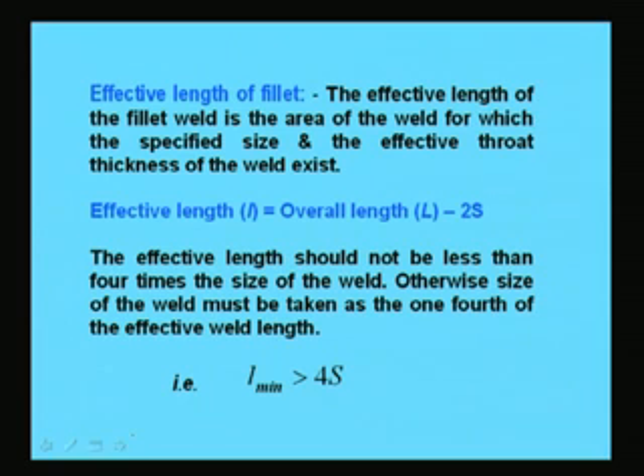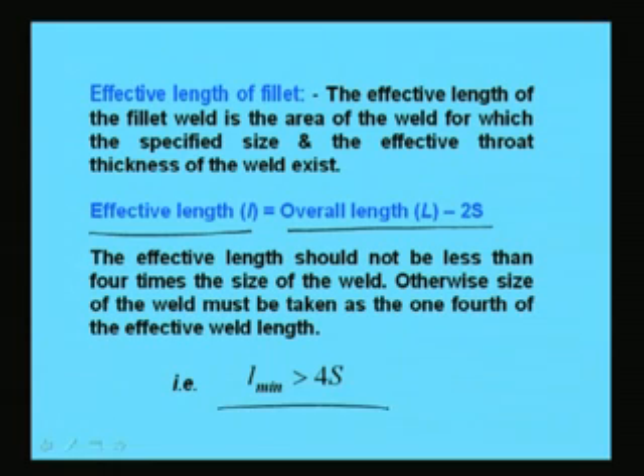Now, another important parameter is the effective length. The effective length of the fillet weld is the length for which the specified size and the effective throat thickness of the weld exist. That means the effective length will be the overall length minus 2s. So when we calculate the length for design purposes, the effective length will be the overall length minus 2s. The effective length should not be less than 4 times the size of the weld. This is another condition given by the code, that the minimum length should be greater than 4s, where s is the size of the weld.